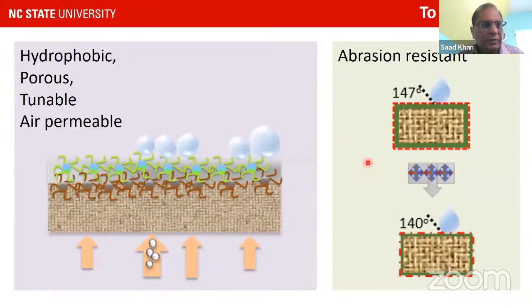So let me summarize then. We have developed a coating. It's tunable. We can add fumed silica as part of the coating formulation. It's porous, it's hydrophobic, and the best part is its abrasion resistance. And so the companies we have worked with have taken this a step further and have been using that to their advantage in coming up with their own formulations. So let me end here.